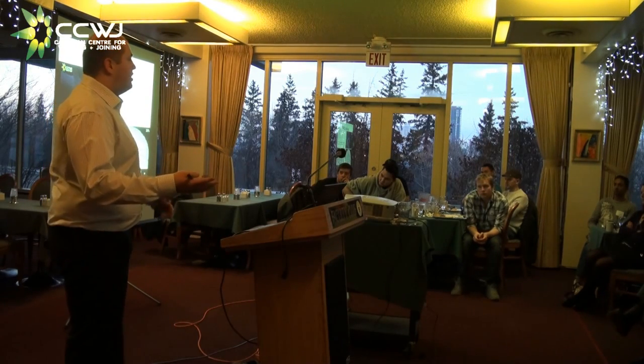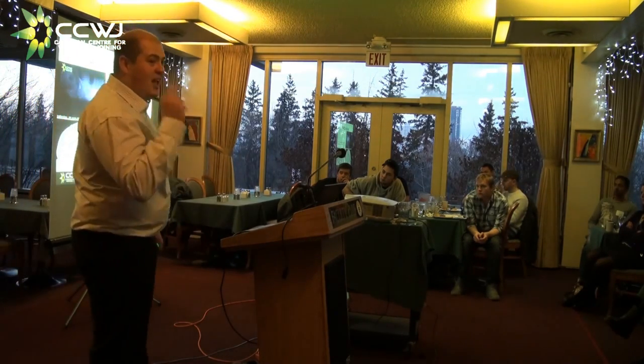Now, one interesting thing is when you do the mass balance between the 2 wires we were welding with, it predicted 36% that we'd end up with in the weld deposit. With Matt's program, we can actually measure. We got 36%. Everything is lining up perfectly when we account for that 20% non-wetting losses.